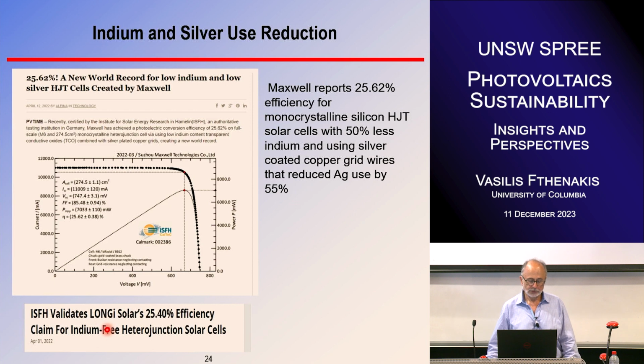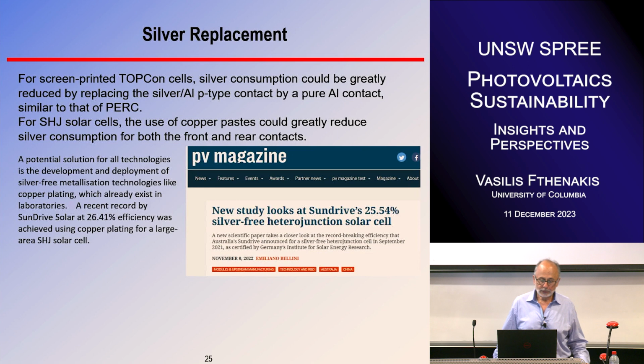Also, Longi has produced, at least in the lab, this type of cells that use almost no indium. Now, silver. With silver, we're talking about replacement because silver is very expensive and limited, and I think the market already uses about 20% of the silver production. So there is a lot of R&D on replacing silver with aluminum or copper. As you know, you have an issue with the contacts, whether they stick so well and so on. But there is a lot of research going on, and even an Australian startup like SunDrive has broadcast that they can go completely silver-free in silicon heterojunction by using copper and aluminum. And Georgia Tech, for example, which Martin knows very well, is trying to do this now, a project from Seto and others as well.